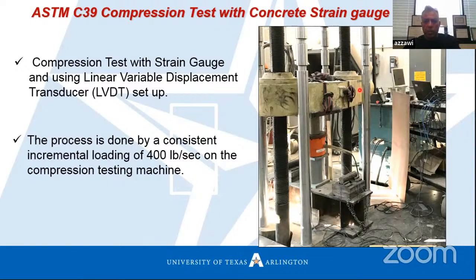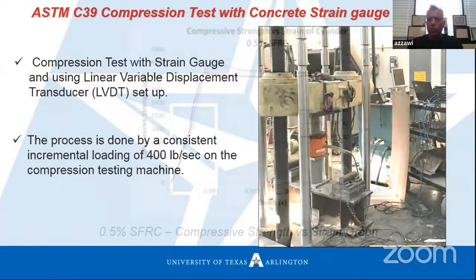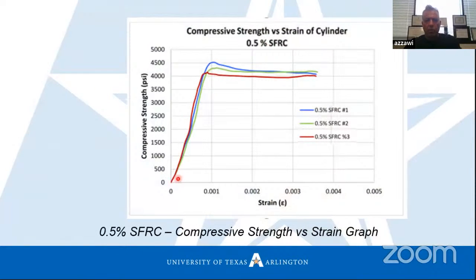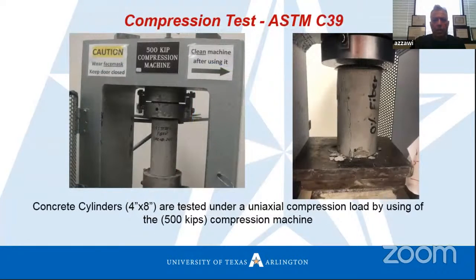This machine is the compressive test machine. We apply around 400 pounds per second as a testing load, and this is the curve we produce for this type of concrete. This is for the 0.5% steel ratio. Then we make a regression analysis to find the modulus of elasticity for this type of concrete. Also, we finished the compressive test based on ASTM C39.